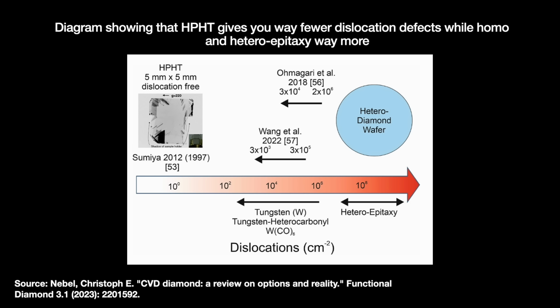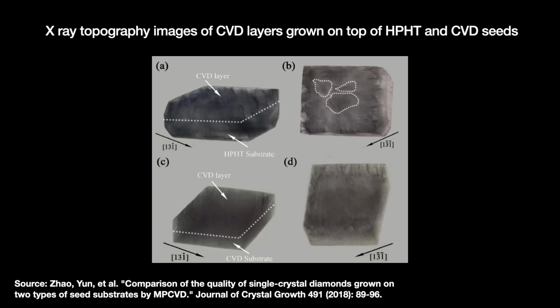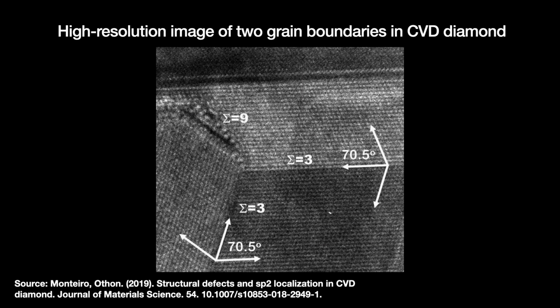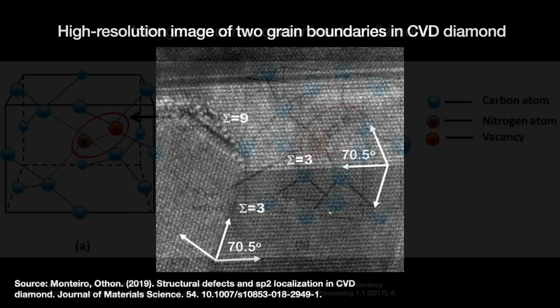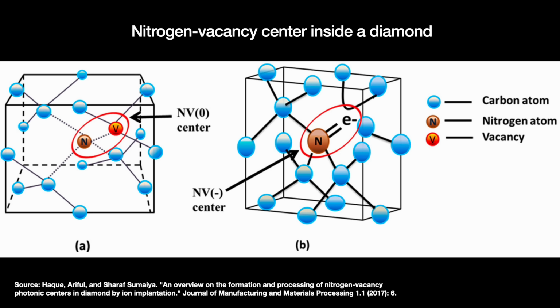Most seeds are produced with HPHT, which grants us the single crystal structure we want, but inherently limits their size. And the complex dynamics of the gas precursors inside the chamber mean that single crystal diamond growth via MPCVD is slow, 75 micrometers per hour without nitrogen, about twice that with nitrogen, though nitrogen doping only goes so far because too much can lead to deficiencies like what are called nitrogen vacancies.